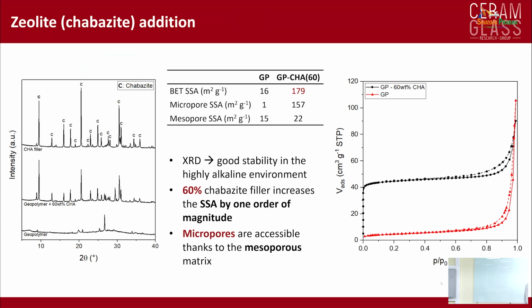Here we simply used chabazite, which is a zeolite. This is very cheap and comes from simply digging up from the ground. And the powder is very fine, so we have a limit as to the amount that we can add. Typically, this limit is about 60 weight percent, which is similar to the volume percent, with respect to the geopolymer matrix. But we also need some matrix to provide strength.